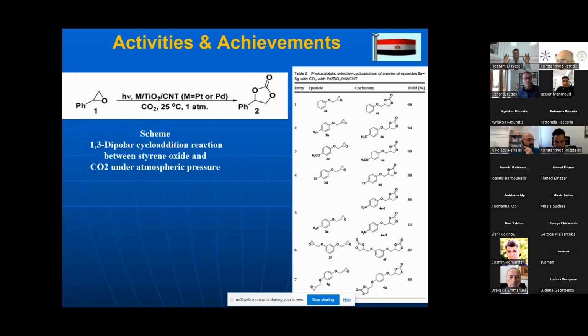The first is transformation of styrene oxide to cyclic carbonate. Second is fixation of CO2 to the styrene compound to form a valuable compound of carbonates, and we have prepared many derivatives. And as we see, the yield in some cases exceeds 98%. So this is a good yield.